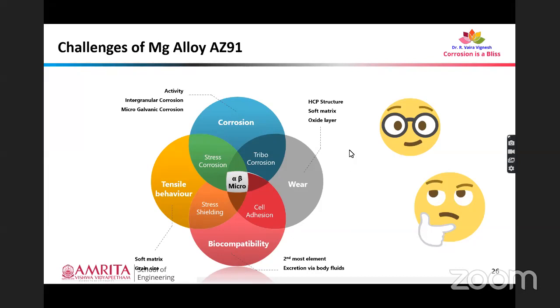So that will result in a high corrosion rate in materials. Generally, when AZ91 is manufactured, we'll end up with a continuous network of beta phase in the matrix material. So that has to be engineered to get a proper corrosion rate. Added to that, if this beta phase is present as a continuous network, we'll have limited tensile strength and hardness. But if it is completely dispersed as fragments within the matrix, then it will improve the tensile strength and hardness of the material too.